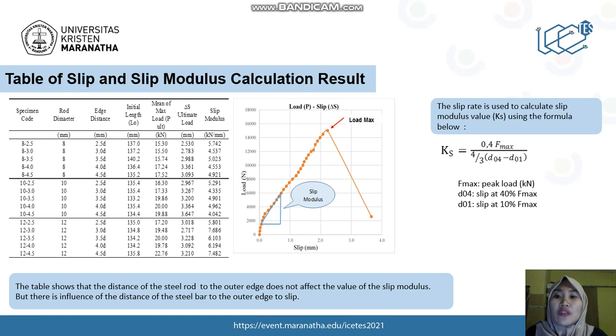This is the table of slip and slip modulus calculation result. The slip data we get from the pull-out test is used to calculate the slip modulus value, or KS, using this formula, where Fmax is the peak load, D04 is the slip at 40% Fmax, and D01 is the slip at 10% Fmax. From the slip modulus calculation result, we find that the distance of the steel rod to the outer edges does not affect the value of the slip modulus. But there is influence of the distance between the steel rod and two outer edges on the slip.